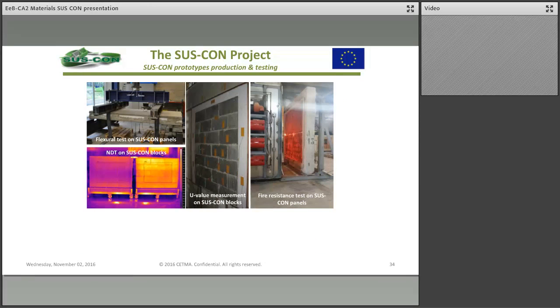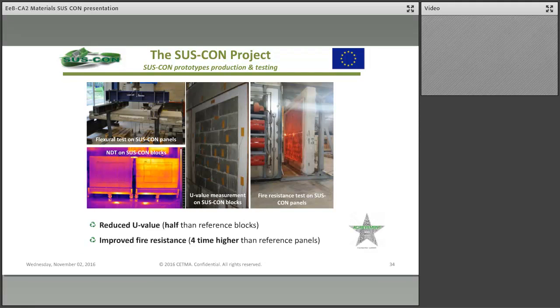In terms of characterization of such prototypes, we found that the Suscon blocks have a reduced U value that is half of the reference commercial block, and the Suscon panels have an improved fire resistance that is 4 times higher than the reference commercial panel. Suscon panel have fire resistance that is EI 240, while the reference commercial panel have a fire resistance that is EI 60.